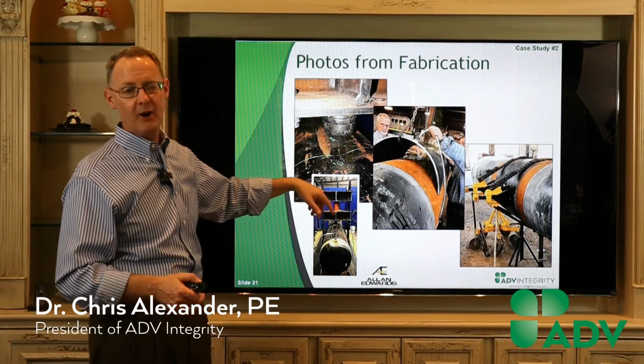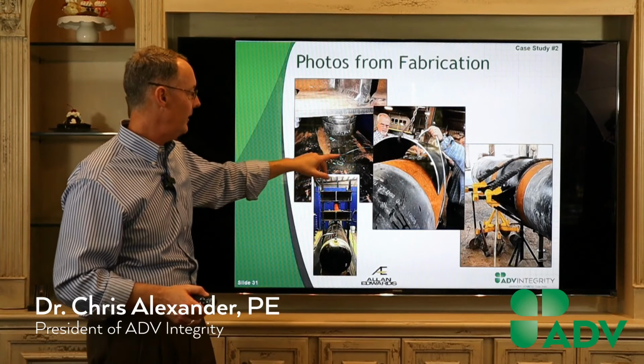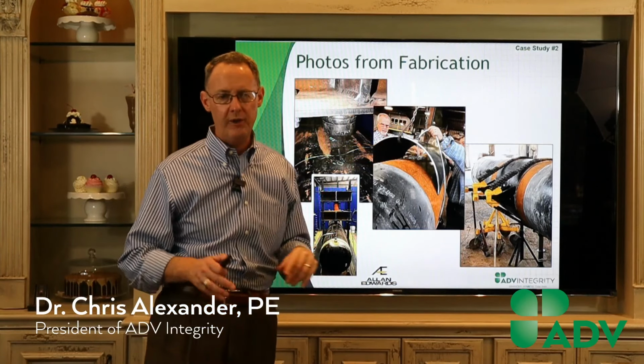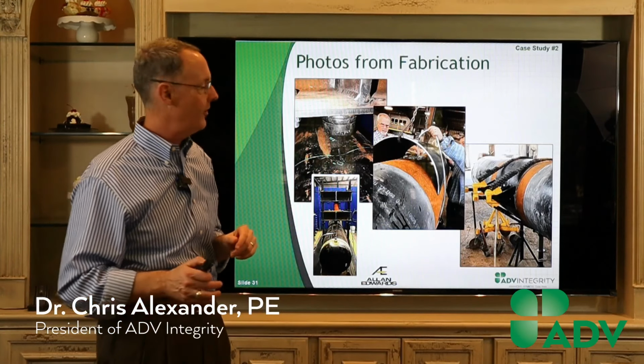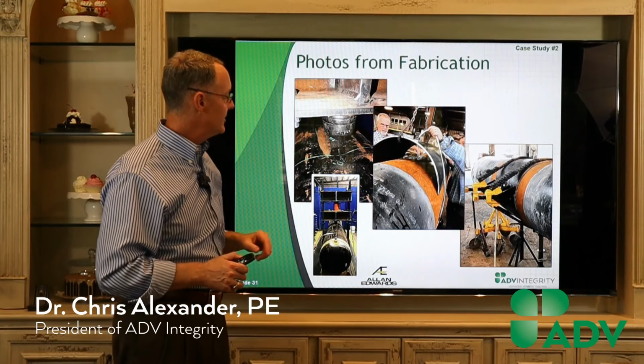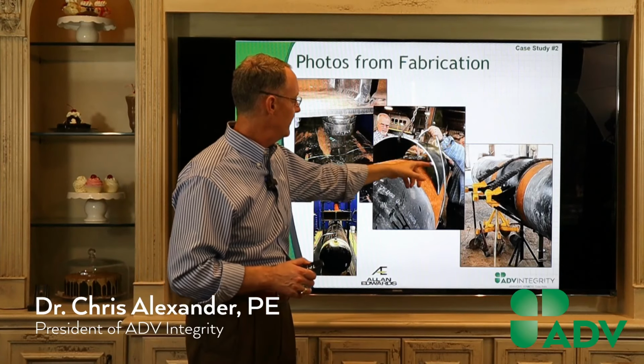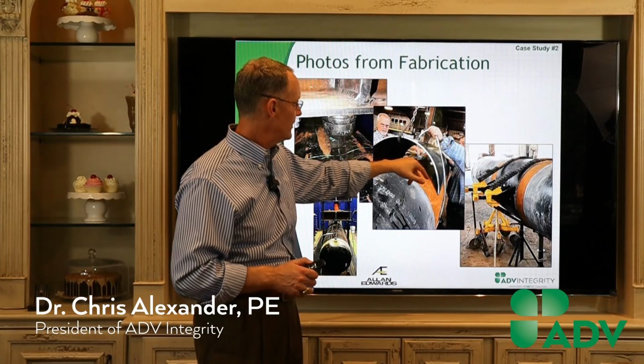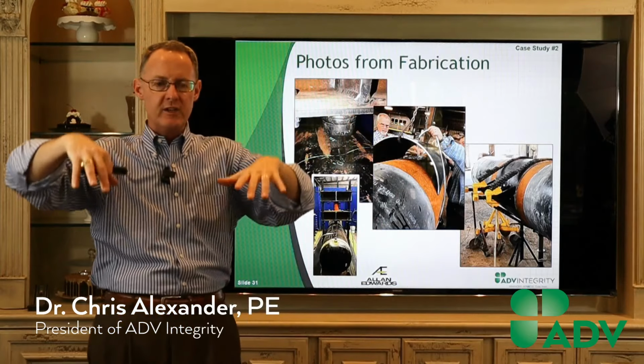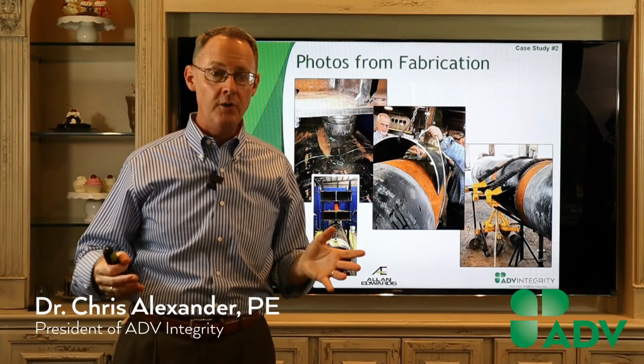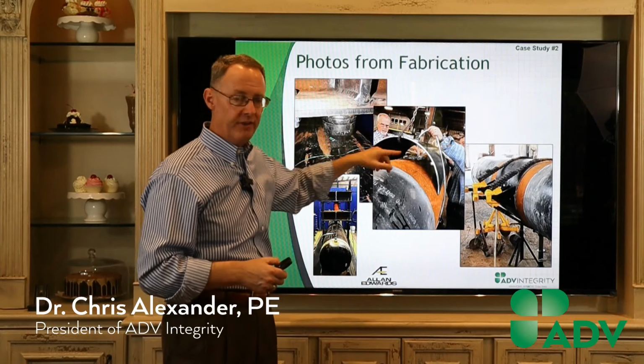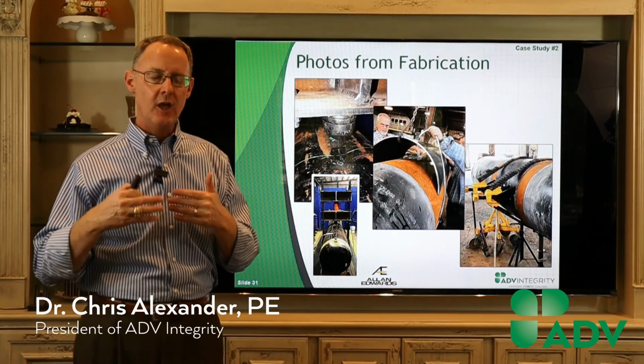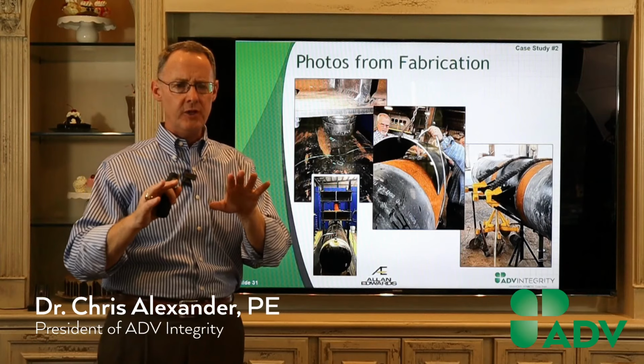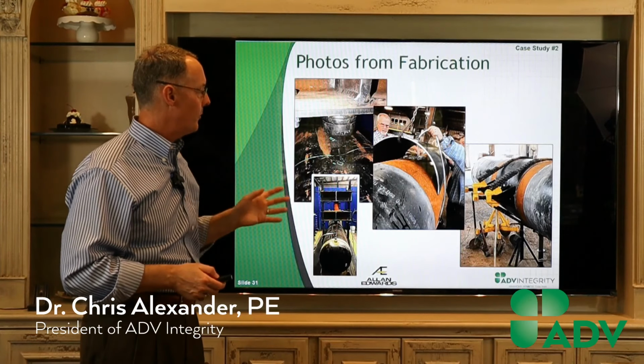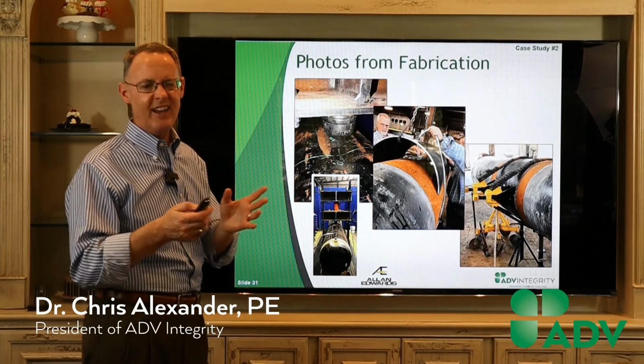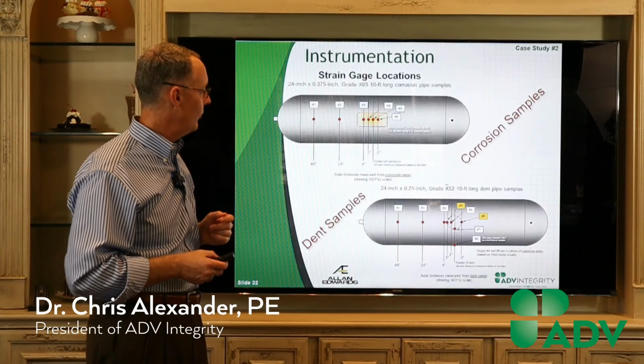I think we actually painted our rig since then, but you can see this is kind of pre-painted. This is Harry Ludwig at PT Welding, who's made many samples for me over certainly the past decade. We've got strain gauges here, and this is Chip Edwards, who's president of Allen Edwards. He's holding the wires as we lower this sleeve onto the pipe, and then we weld it up. Those strain gauges are very important because they tell us what's going on underneath the steel sleeve in the dent. Great program, done a lot of these, and after a while you kind of get a pattern, and it seemed to work very well.